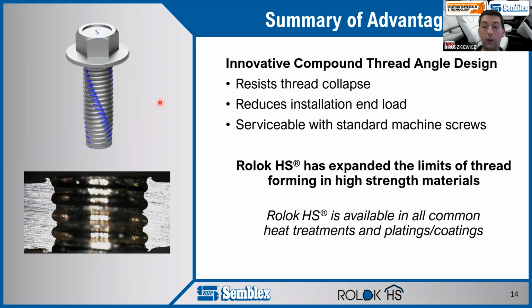So in summary, Rolok HS is a new thread forming fastener. We just started releasing it this year. It is resistant to thread collapse because it uses that compound angle thread, where the top angle changes our loading from bending into compression. So even if we do compress the thread a little bit, it still drives. It does reduce the installation end load simply because the threads aren't failing. When you start to bend those threads over on a traditional thread rolling screw, you have to push really, really hard to get it to go through the part.